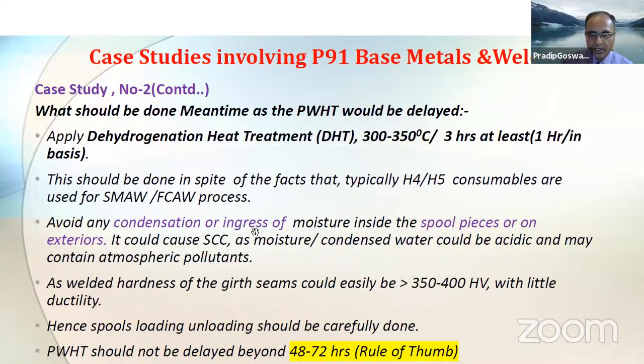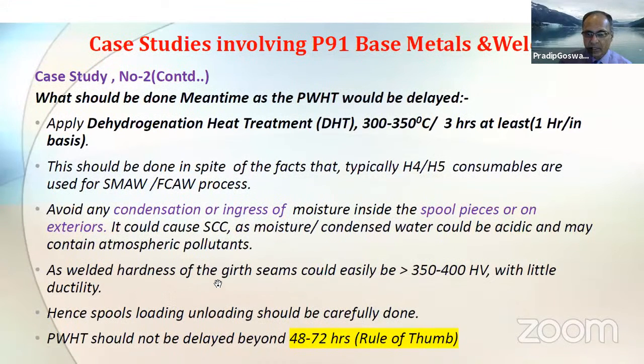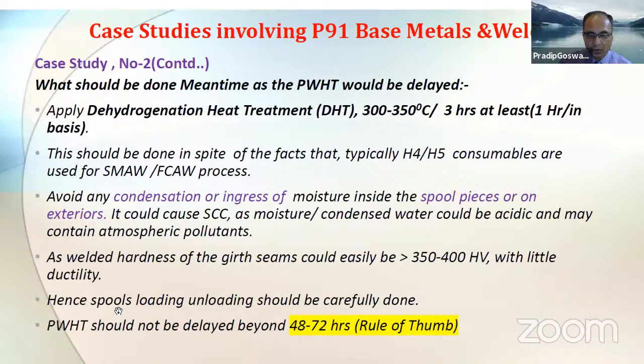Avoid any condensation or ingress of moisture inside the spool pieces or on exteriors. This could cause SCC, or stress corrosion cracking, as condensed water could be acidic and may contain atmospheric pollutants. As-welded hardness of the girth seams could easily be 350 to 400 HV with little ductility, hence the spools' loading and unloading shall be done very carefully. Post-weld heat treatment should not be delayed beyond 48 to 72 hours, typically, as a rule of thumb.